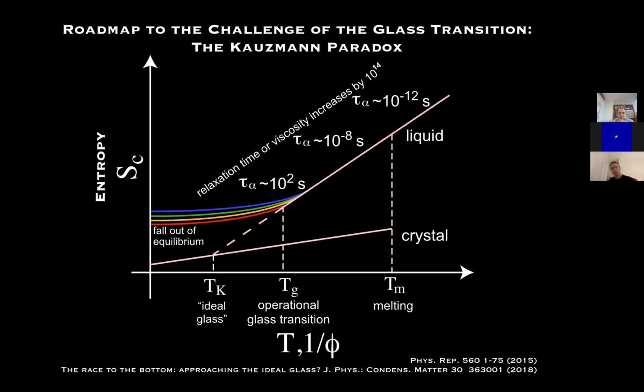So let me try to explain the problem with glass. For me, it's captured with this slide. So there are various things happening on this slide, and I'll try to walk you through it. There are two lines, the pink lines. One is liquid, one is crystal, and what is plotted is the entropy of the material, or to be more precise, the configurational entropy of the material. So in some sense, this is a measure of the number of configurations available to the constituent particles which comprise the material. And a liquid has a higher entropy than a crystal because there are more configurations available to it, or another way to put it is that it's more disordered.